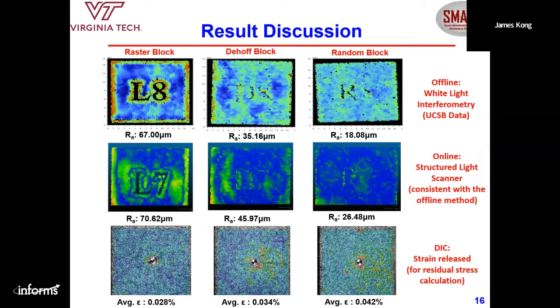And here I just show some of the results from our 3D printing using the 3D scanning technology. The first row, those three again, are not images, they are point cloud data. They were captured using the white light interferometers, which is very accurate, but very time consuming. That's from our collaborator at UCSB. They have this advanced equipment, and this part is only 15 by 15 millimeter of surface area, but scanning each of them needs about a couple hours, which is very, very time consuming.